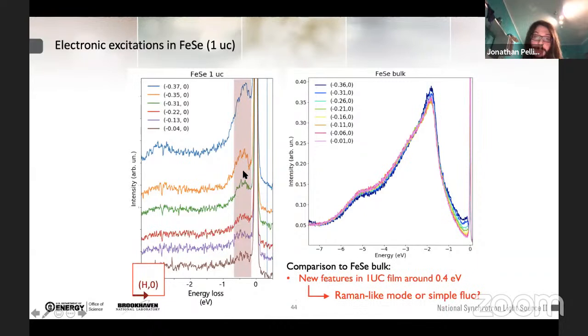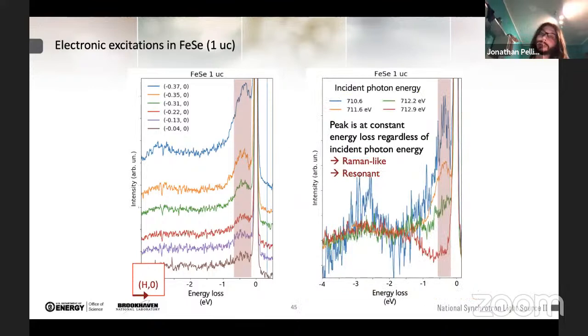However, one of the questions that might emerge is whether this is a genuine excitation of our system, in which case it should behave in a Raman-like way, or whether it is coming from an incoherent relaxation of the bands and it would behave in a fluorescence-like way. So because of this, we change the incident energy, which of course tunes the intensity. But this was to demonstrate that the peak at 400 meV is a genuine Raman-like excitation, which means it is a coherent excitation of our system.